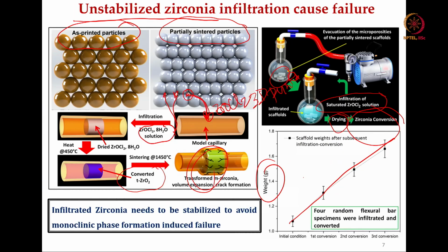This is in contrast to what you have seen in the last lecture, that one can use the infiltration of the zirconium oxychloride solution itself. This zirconium oxychloride 8H2O solution will not give you stabilized zirconia, but it will give you more pure zirconia. And whenever the zirconia particles are unstabilized, this will certainly form monoclinic zirconia after the sintering process is over, right. So, this is what has happened in this particular case.